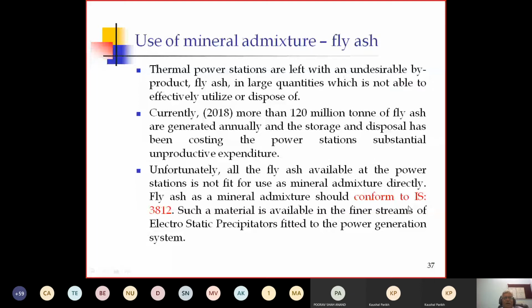Currently in 2018, more than 120 million tons of the fly ash are generated annually, and the storage and disposal has been costing the power stations substantial unproductive expenditures. So huge amount of byproduct that is fly ash is generated by this thermal power station, and its disposal is also a matter of problem. So unfortunately, all the fly ash available at the power station is not fit for use as a mineral admixture directly. Fly ash as a mineral admixture should conform to IS 3812. Such material is available in finer streams of the electrostatic precipitators fitted to the power generation system.